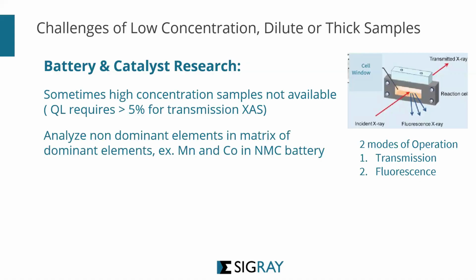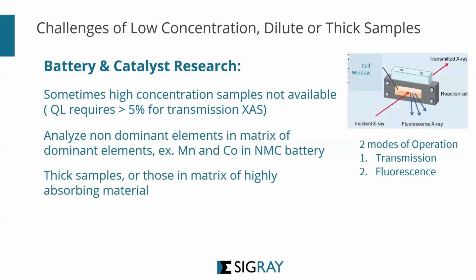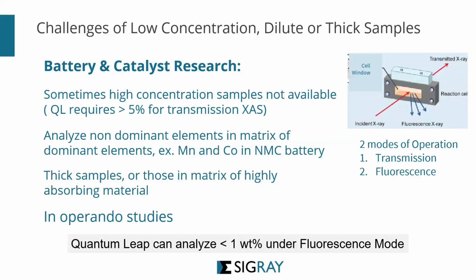So what if you also want to study the non-dominant part of the material like NMC? The manganese and the cobalt of the NMC are in the minority. If you were to study them, the concentration is much lower compared with the whole material. What if you are dealing with thick samples or highly absorbing samples, as well as those where you are trying to run operando studies? So for all these materials, you will need much greater sensitivity, and we can do that under fluorescence mode.